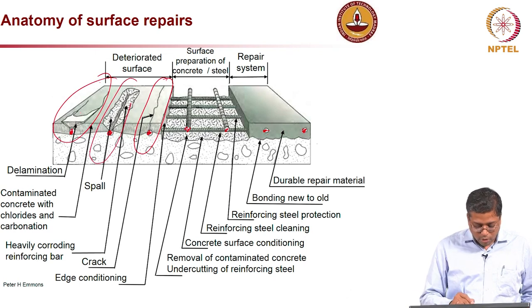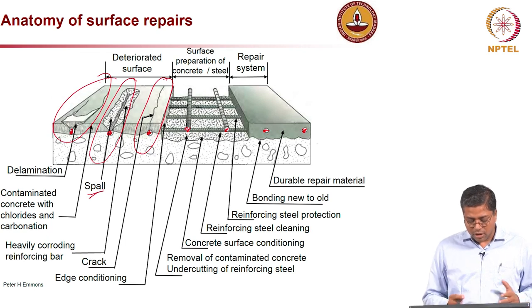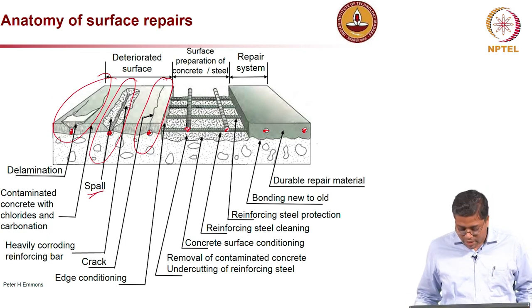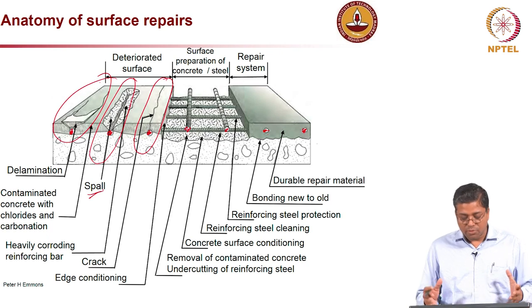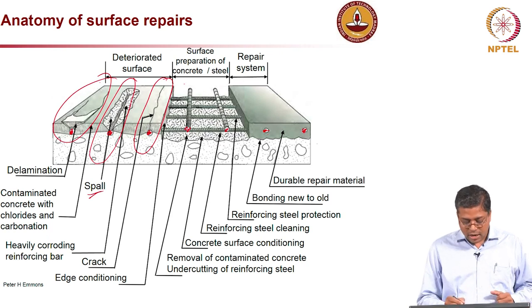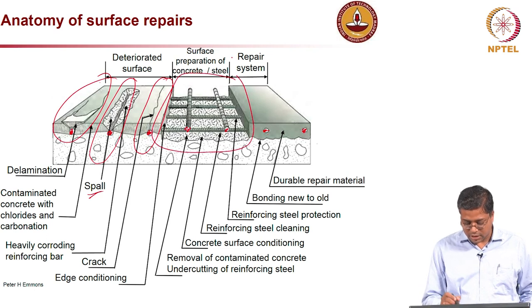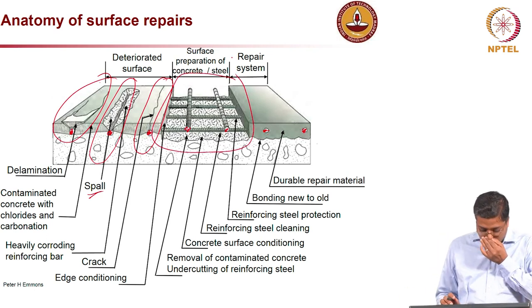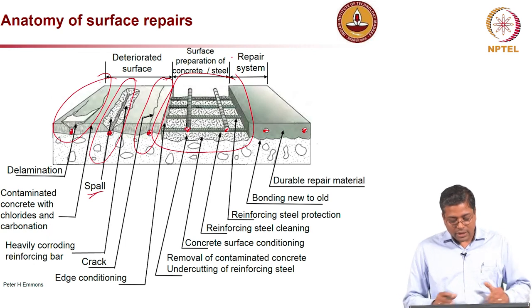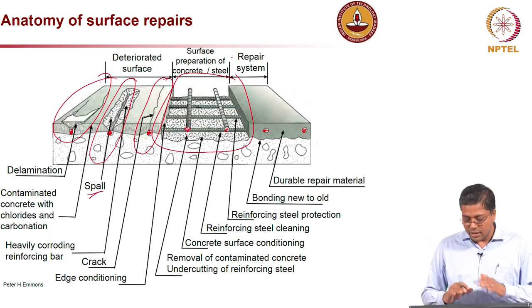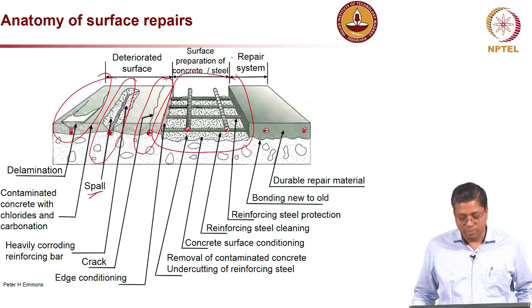which eventually spoils the concrete. And then once it is spoiled, you have to really do a major repair and basically remove the loose concrete, and then cut the concrete as you see here in this section, remove the cover concrete and clean the reinforcement surface, and then apply the new repair material.